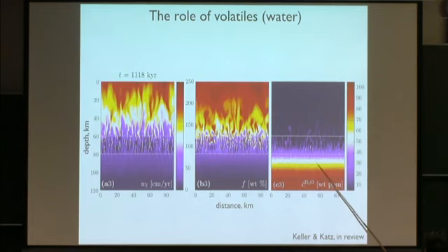And with the melting it gets diluted, and these channels have larger melt content, and that's what makes them corrosive and drives melting there. So we think that this is potentially contributing to channelization, not that there's not important reaction going on in this part of the regime, but that channelization may start even deeper, particularly down here where you have garnet and the different partition coefficients, and this may help to explain uranium series because you may transport melt from deeper at greater speeds.